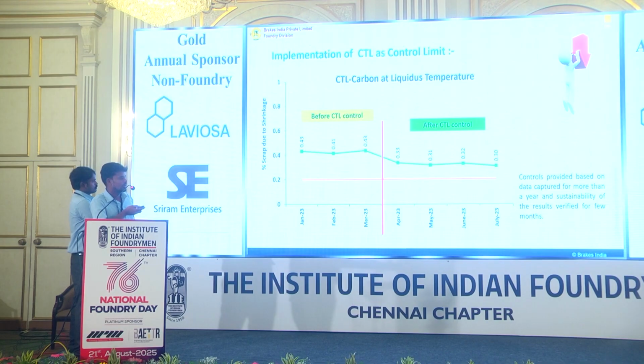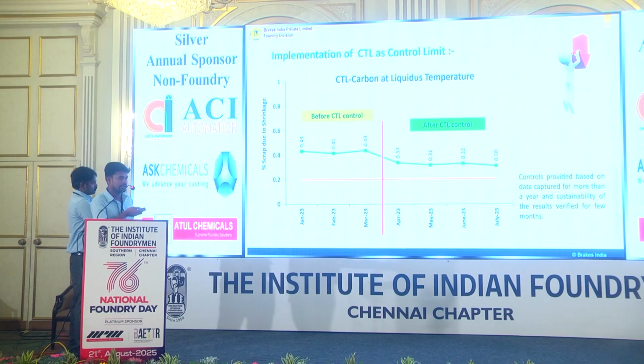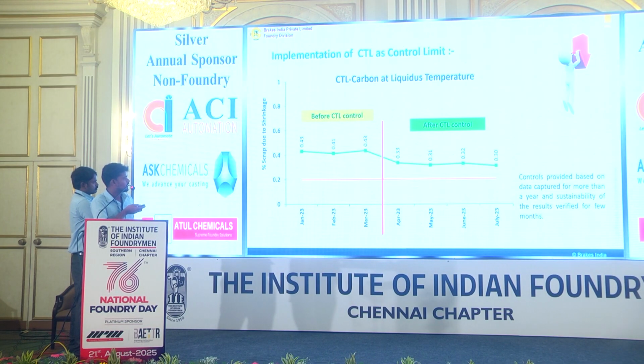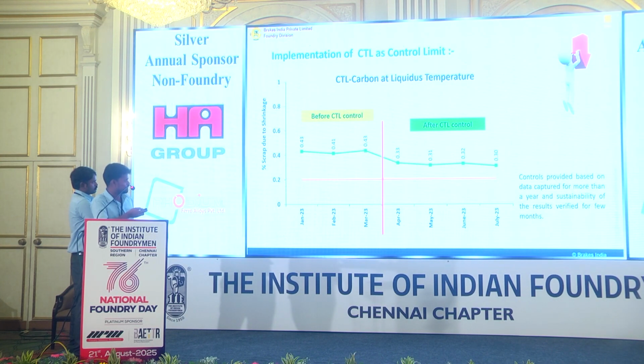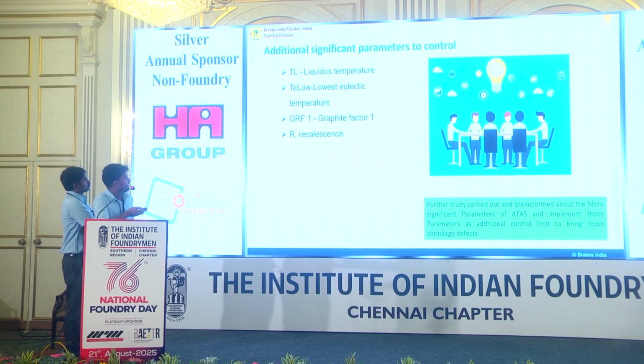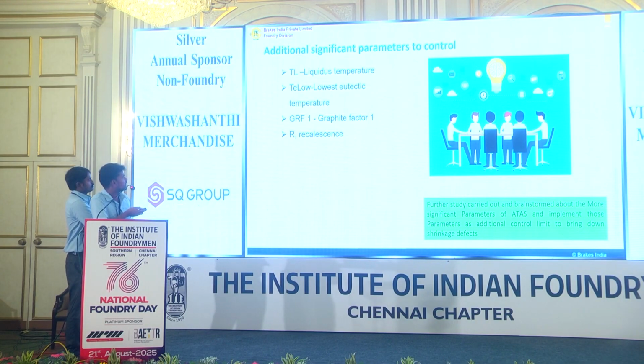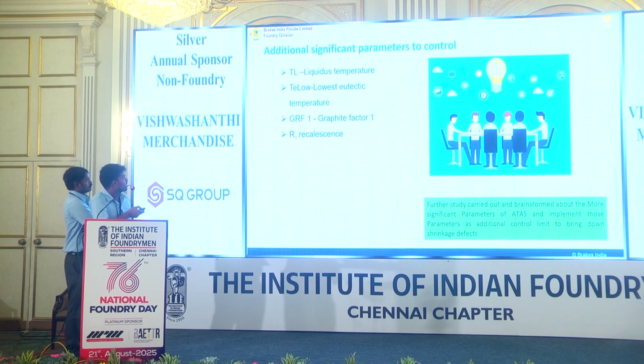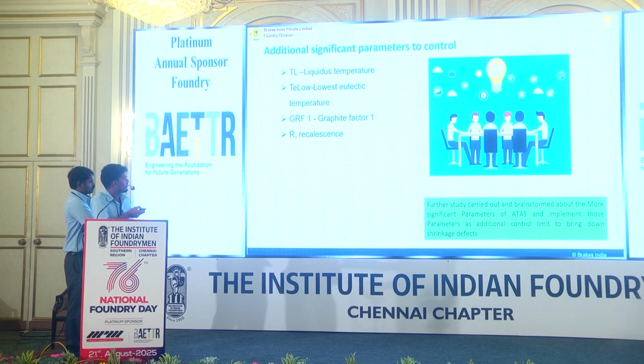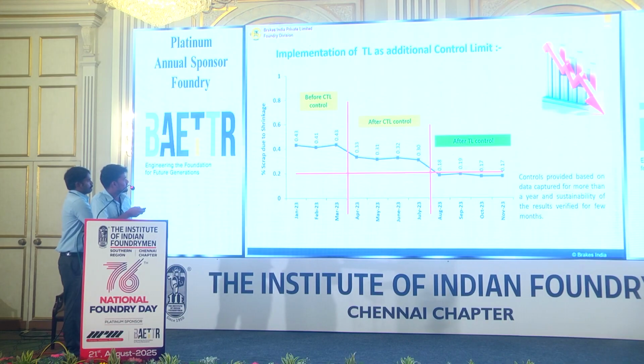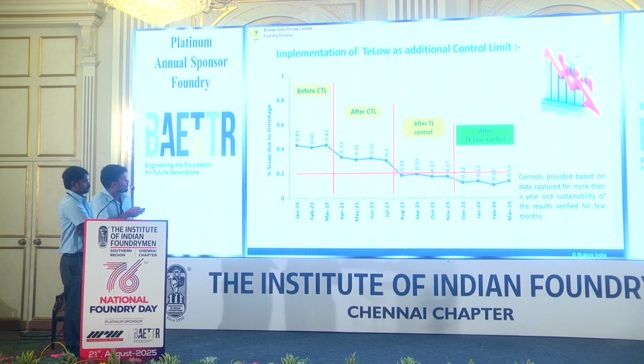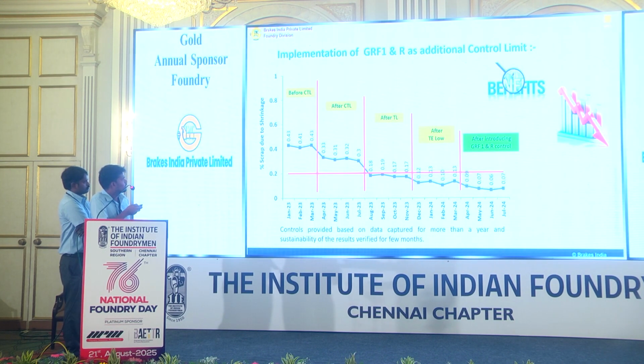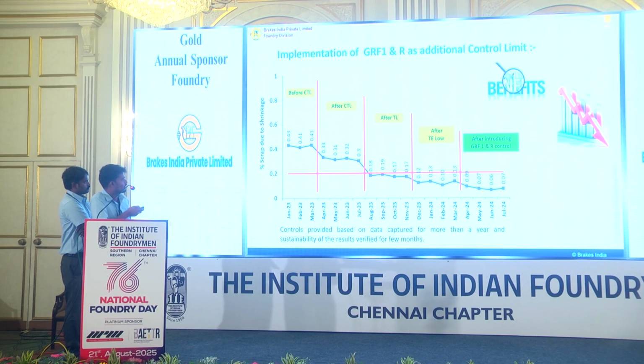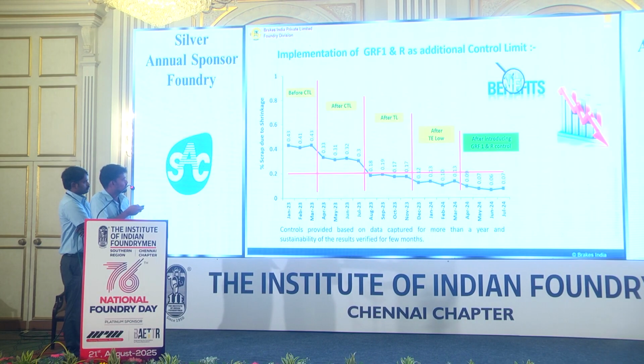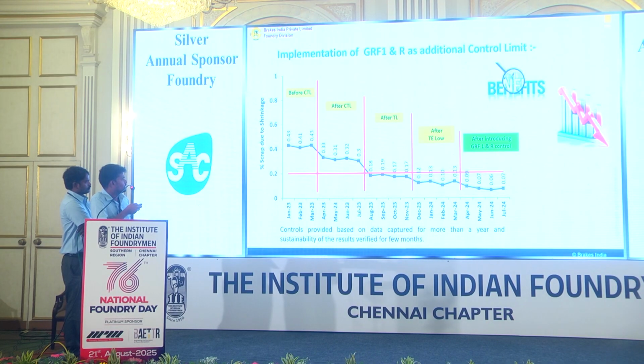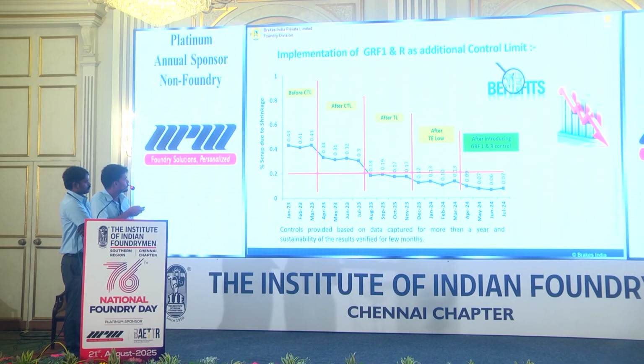These controls are provided based on the data captured from the thermal analysis for more than a year, and we checked the effectiveness of these parameters for a few months. Only then did we take the control into this system. Apart from CTL, we decided on some additional controls along with the CTL. We gave some thermal parameters like TL, the liquidus temperature, TE low, graphite factor, and recalescence. After putting these controls along with the CTL, we drastically reduced the rejection stage by stage. Finally, with the TL control, TE low control, and graphite factor and recalescence control, we reduced the rejection level to 0.07%. Before that it was 0.43%. So we achieved almost 80% reduction in rejection through eliminating sinkage defects.